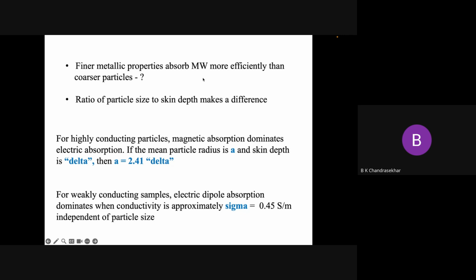For example, if you are having highly conducting materials like gold or copper and things like that, it is not the electric component that dominates the heating, it is the magnetic absorption that dominates the absorption. Therefore, the skin depth, if I call that delta, actually there is a symbol for the skin depth which is delta, but I could not download the symbol, so I just written it as delta in quoted words. So if the particle radius is a, then if you can approximately make the starting particle radius about 2.41 times the delta, that is the skin depth, then you are able to heat the material very efficiently.